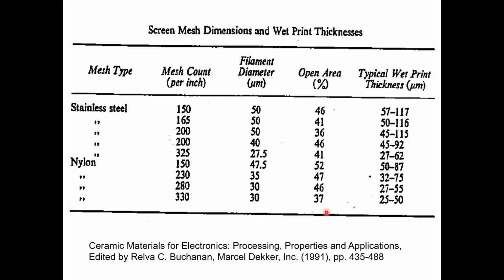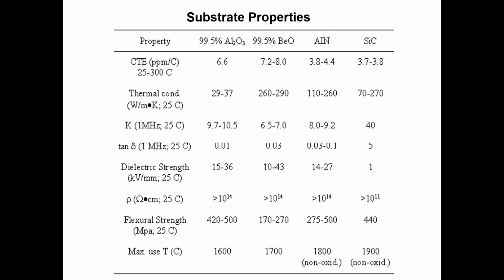In terms of screen specification, you can buy a screen by specifying the mesh number. The higher the mesh number, the finer the screen is. And you can see the filament diameter that makes the screen, percent open area, and typical wet print thickness that you can print through these screens. There are multiple choices of substrate material: alumina, beryllium oxide, aluminum nitride, and silicon carbide. Alumina is the material of choice because you can make it very inexpensively, and it is an insulator. These are all insulators, by the way. You can see the resistivity values at room temperature.